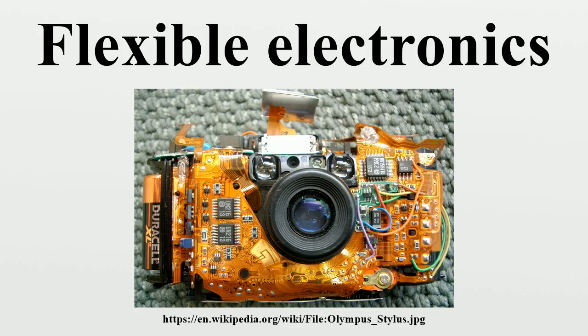Manufacturing. Flexible printed circuits are made with the photolithographic technology. An alternative way of making flexible foil circuits or flexible flat cables is laminating very thin copper strips in between two layers of PET. These PET layers, typically 0.05 mm thick, are coated with an adhesive which is thermosetting, and will be activated during the lamination process.